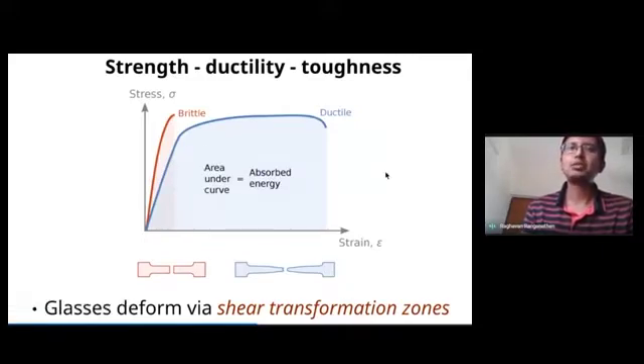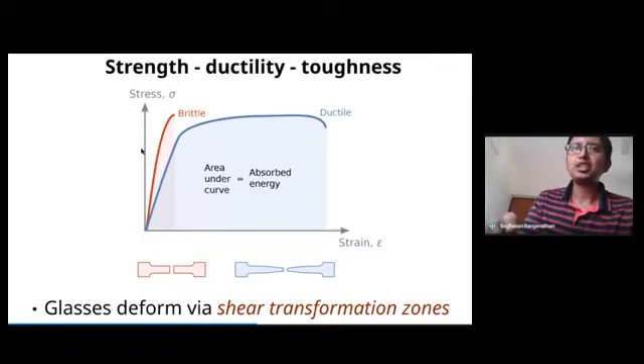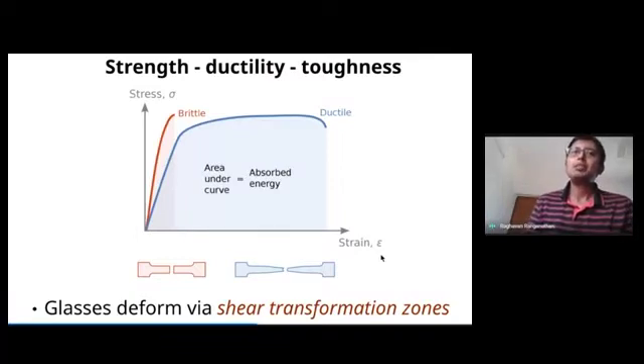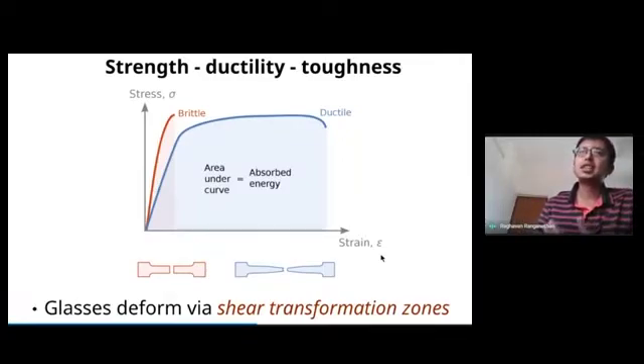Okay. So glass, as we know, is something that's very brittle. And that's got to do with the glass structure that I'll come to in a minute. But essentially, brittle materials show a behavior that's shown by the red curve in this graph. So what we're plotting is the variation in stress of a material as a function of strain or the deformation that you impose on the material. So a brittle material like glass basically does not show a large amount of extension. It just catastrophically fails or breaks at some particular strain. That's what the red curve shows.